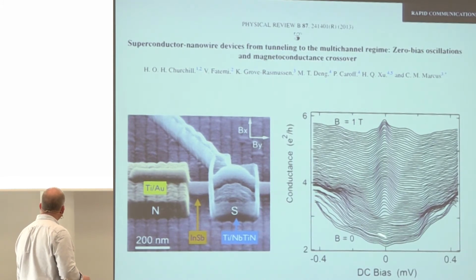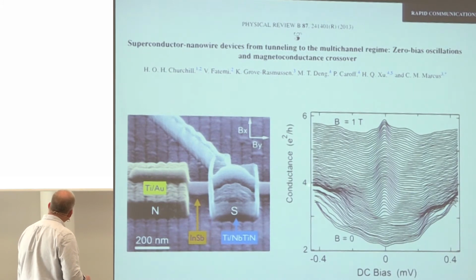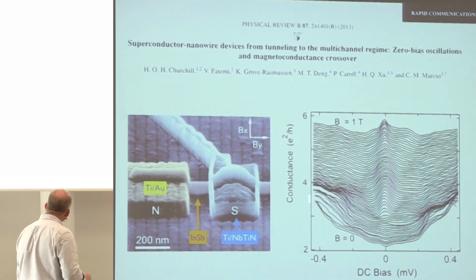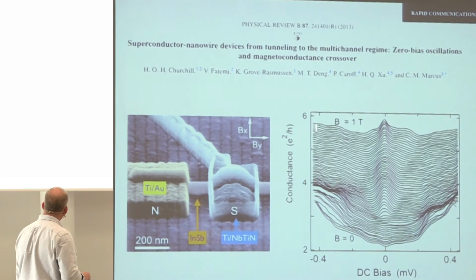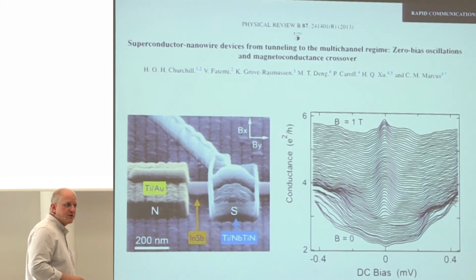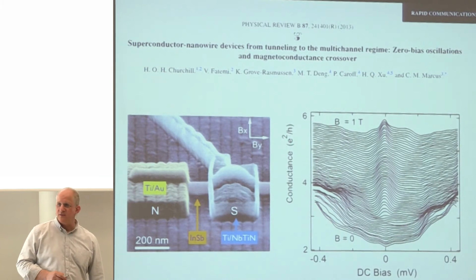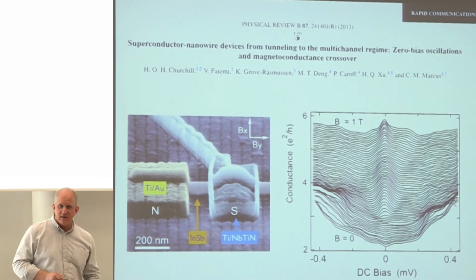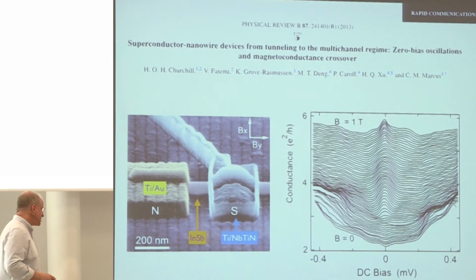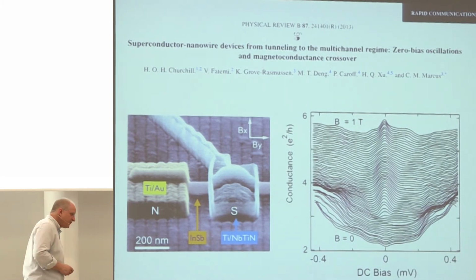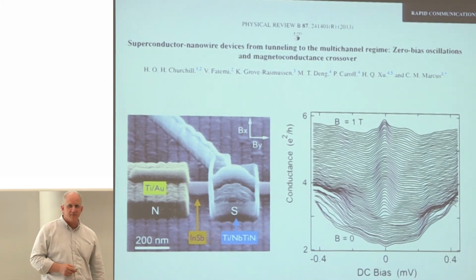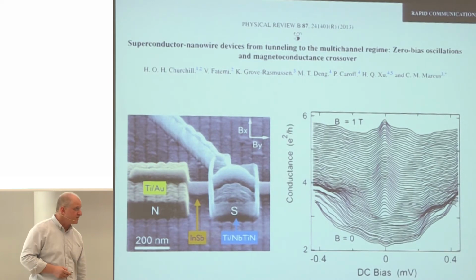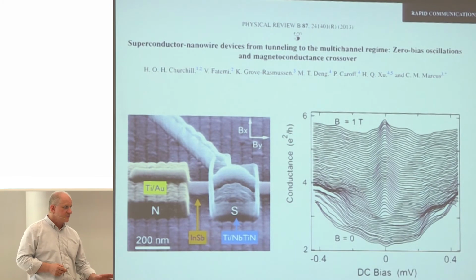But as you turn up the magnetic field, this is not a particularly good density of states, nor is this a very deep tunneling regime. In fact, it's a highly conductive regime. But boy, you just can't help but turn up the magnetic field, and all of a sudden, boom, this density of states would produce a peak, and you just couldn't get away from it. So if anybody has any doubts about the Delft experiment being reproducible, let me tell you right now, it's hard to not reproduce it.